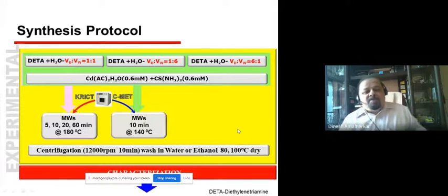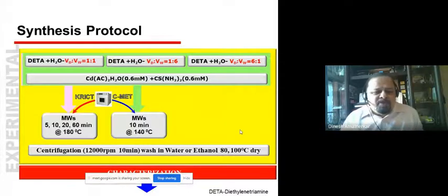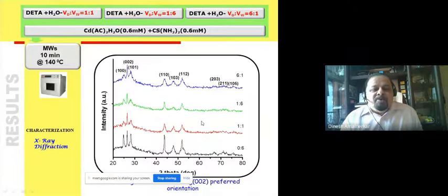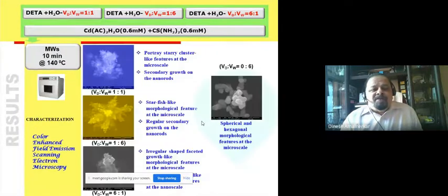Now, after doing all these experiments, I returned to India and asked another PhD student, Dr. Manish Shinde, who is again a scientist at CMET. Anyway, it's a microwave reaction, and we have a microwave digester, something similar to the one at the Korea Institute of Chemical Technology, at my institute. So why not go for 140 degrees centigrade instead of 180 degrees centigrade? He did that. With just 10 minutes of heating, we could get the same result, 002 preferred orientation, and these are color enhanced SEM images obtained maybe in 2010.